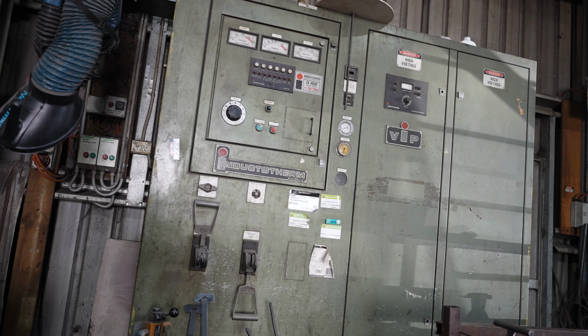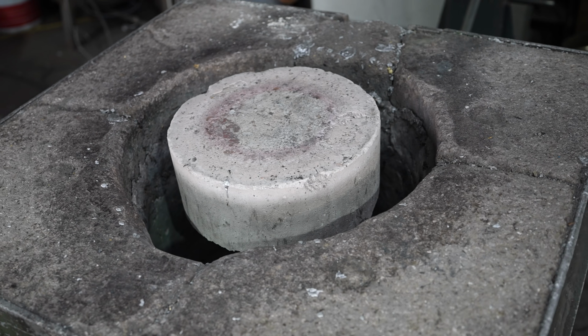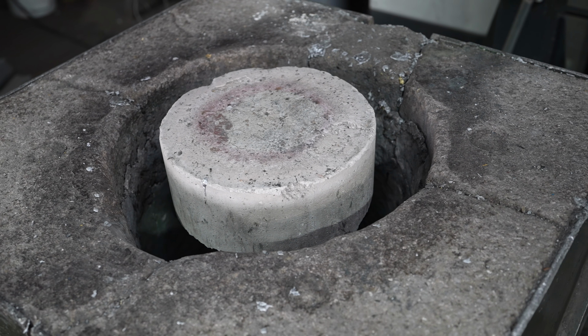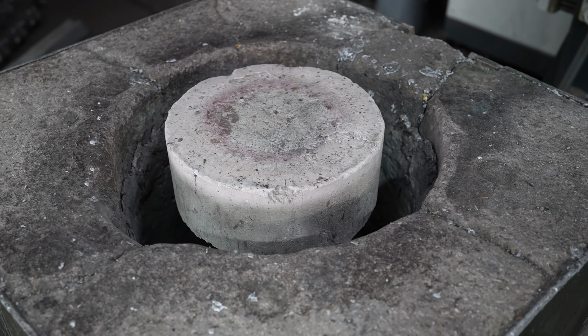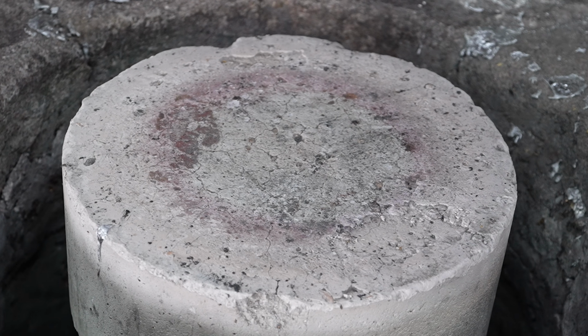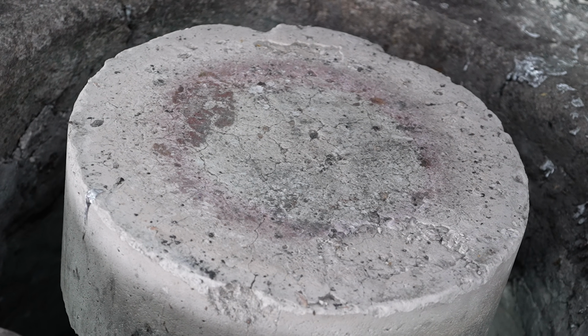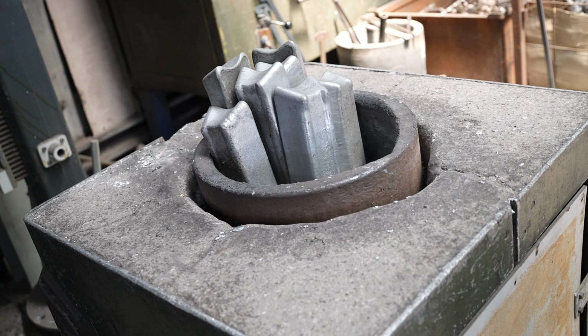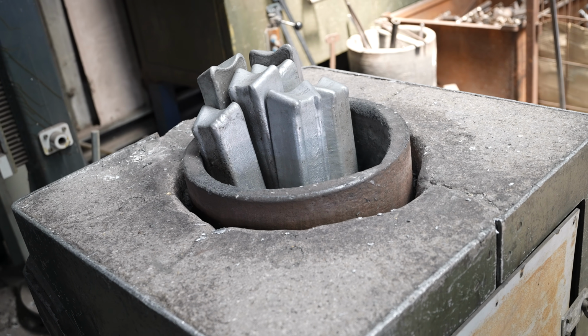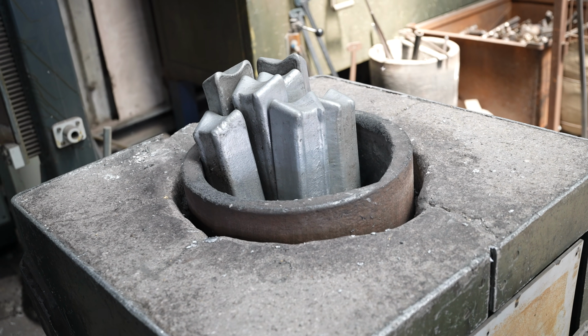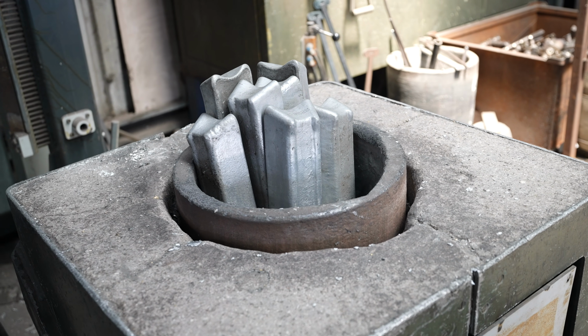So we melt with induction, and the way induction works is we've got this power pack here. That power pack powers this furnace. So this is our non-ferrous furnace where we do all of our non-ferrous casting, so your aluminiums, your bronzes and brasses. And the way it works is it's got a copper coil that's around the furnace there, and that power pack generates a really large magnetic field in that copper coil, and that magnetic field generates eddy currents in the metal. And those eddy currents are what cause the metal to heat up and melt it. So it's much more efficient than a resistor-based furnace, which is like a glorified toaster.